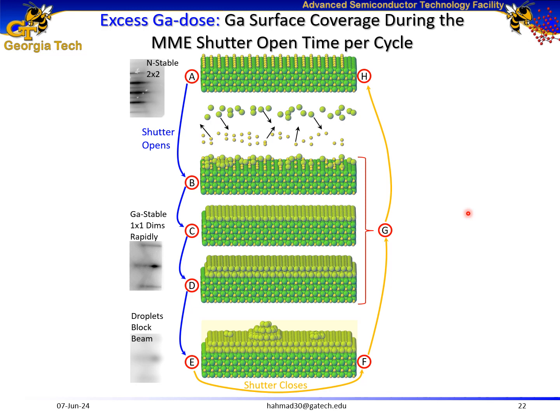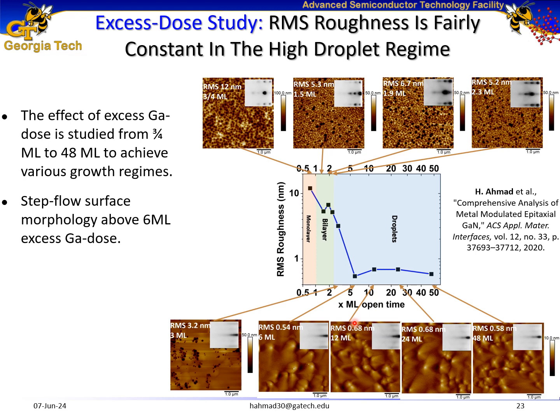gallium dose per shutter cycle, which is our second growth parameter. I want to introduce excess gallium dose first. So in metal modulated epitaxy, we start from a stable surface, then we open our shutter, which results in adsorption of gallium in multiple stages, and excess gallium dose is the gallium surface coverage during the MME shutter open time per cycle. So I studied the effect of excess gallium dose from 3/4 of a monolayer to 48 monolayers, and from this study I found that we achieve step flow surface morphology above 6 monolayers excess gallium dose.